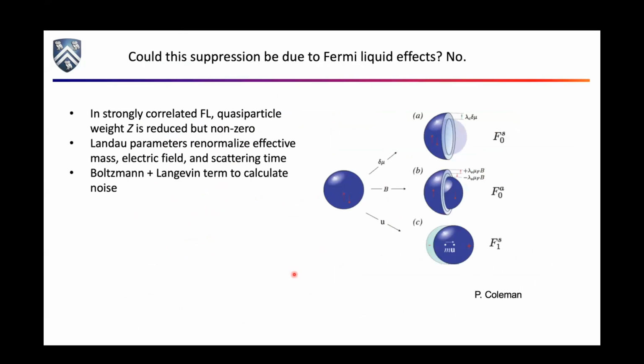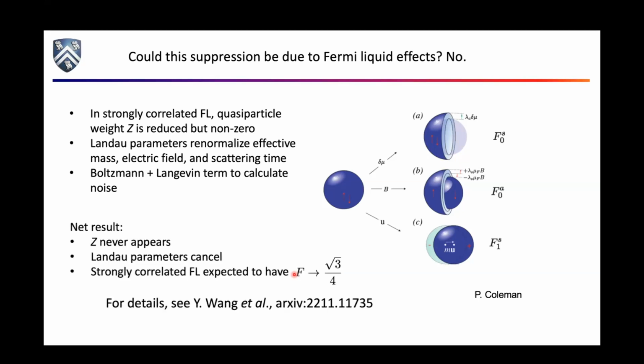Is there a reason to think that this is just some funny Fermi liquid thing, where we have much stronger interactions than are usually considered? Even though I would tell you that phenomenologically this is in the non-Fermi liquid regime, you could ask yourself, what if it was just a Fermi liquid? You carry this through, and this is work people in this room have done, working with Qingyan. Bottom line, the strongly correlated Fermi liquid, where the quasi-particle weight is suppressed but not all the way to 0, should still give you √3/4 from the quantum factor.